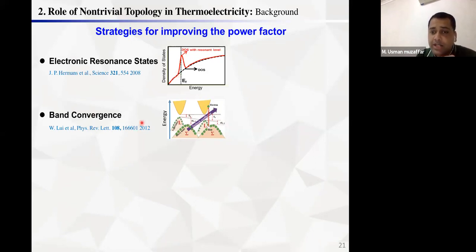Another strategy to enhance the Seebeck coefficient, to optimize the effective mass, is band convergence. Consider we have a SnTe system, and it consists of two valence bands: the light hole band that lies at the L point, and the heavy hole band at the sigma point. You can see that the heavy hole band is far away from the Fermi level, so it is not contributing too much in the transport. So we need to do doping so that we can reduce the energy difference between these two bands, so that this band also contributes to the Seebeck coefficient.